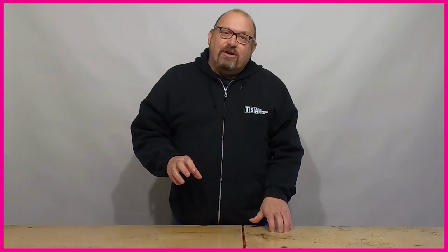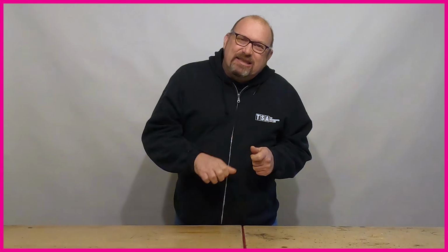By using finer granules during the sintering process, you end up with a denser material with smaller pockets of air. This creates a harder and more durable base. However, because of that increased density, it's a base that's also harder to wax as those air pockets are smaller. So you've really got to work the wax in a lot more than you would with a regular sintered base. However, once you've got that wax in there, it's going to stay in there a lot longer. So you're not going to have to wax it anywhere near as often.